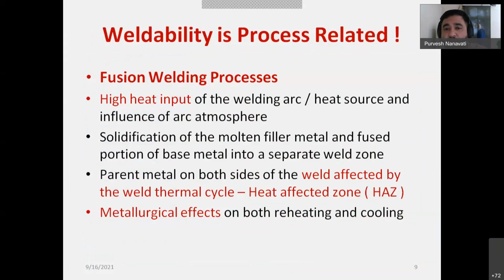How? Because the fusion welding process involves high heat input of the arc or from the heat source. So there will be a solidification of the molten filler metal, and the fused base metal will be separate, and the heat affected zone. The heat affected zone is developed because of the thermal cycle. So metallurgical effects are both on heating and cooling, because during welding the material is heated up, and during cooling it contracts. So expansion and contraction also produce residual stresses, and the material's grain structure is also affected by the thermal cycle. So there is a metallurgical effect due to the heat input, is what I want to convey.